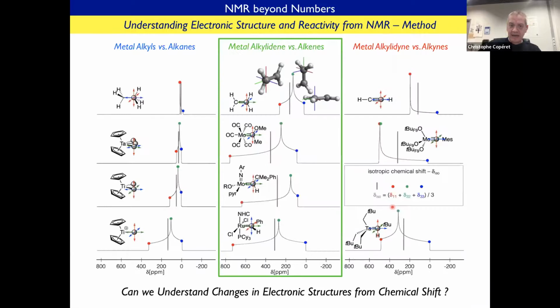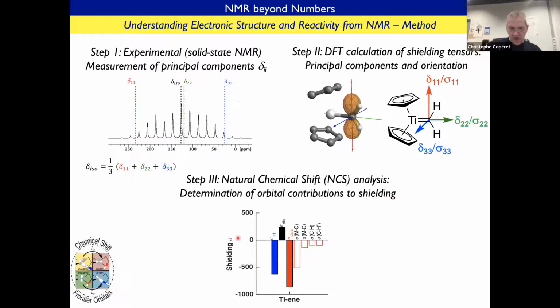So now let's dive in and try to understand the origin of this very large chemical shift anisotropy in this metal carbon double bond. And I chose this example today in honor of my very good friend Dick Schrock, who is also a very good colleague and friend of Bob Griffin. So the way we are going to do that in our laboratory, and I'm not going to go into the detail, is that we are going to measure the powder spectra at a low spinning rate to be able to extract the principal components of the chemical shift tensor.